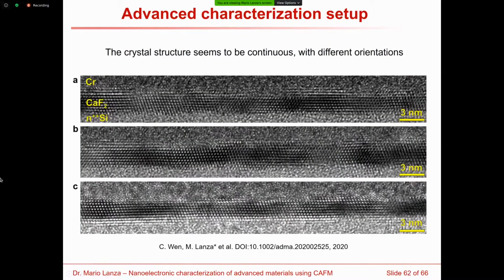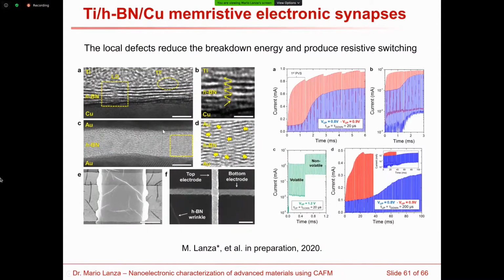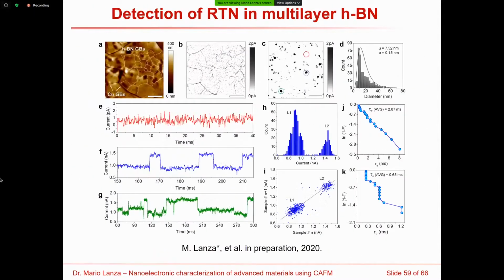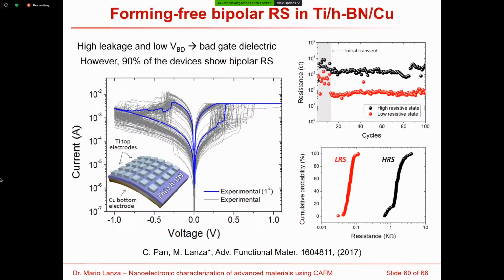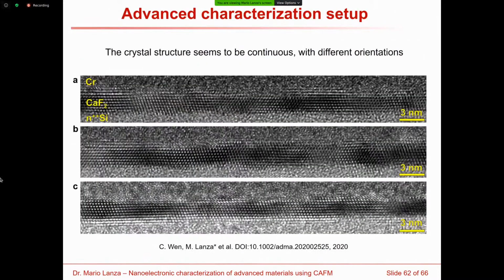So we found that the boron nitride was very useful to be used as resistive switching layer. However, it cannot be used right now as gate dielectric in field effect transistors due to the presence of defects, as you can see in these TEM images and in the current maps that I was showing before. So because the methods that we are using right now to produce this material at the wafer scale, which is chemical vapor deposition, are still producing samples with high density of defects, we started to explore also other potential candidate materials as gate dielectrics in 2D materials-based field effect transistors.